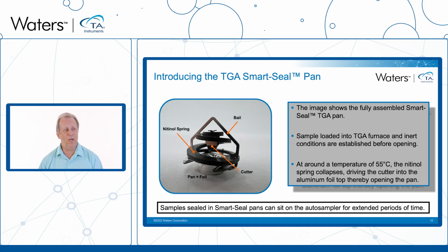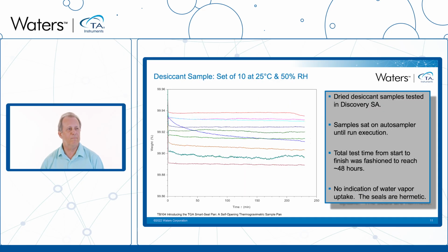Once this pan is loaded into the TGA, we typically purge for a specific period of time in order to get the TGA furnace down to inert conditions. And again, raise the temperature slightly to actuate the nitinol driving the cutter through the aluminum foil. And then this TGA is run as normal. And of course, samples that are sealed within these pans can sit on the autosampler tray for extended periods of time.